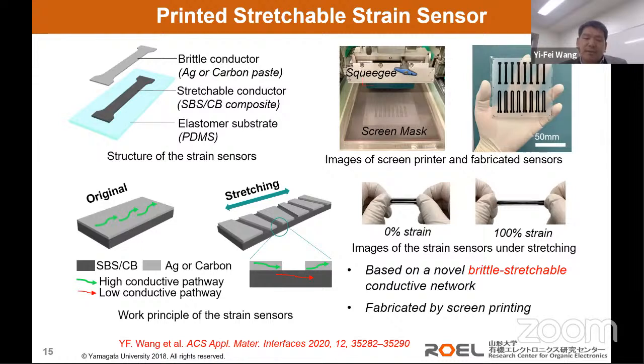And then for the bottom layer, we use a stretchable conductor. This layer's conductivity is lower than the brittle layer, but it still keeps good conductivity even under high stretch conditions. So in that case, the device can keep working even at a very big strain. So this sensor can stretch to 100%, and this sensor was realized by a screen printing process.